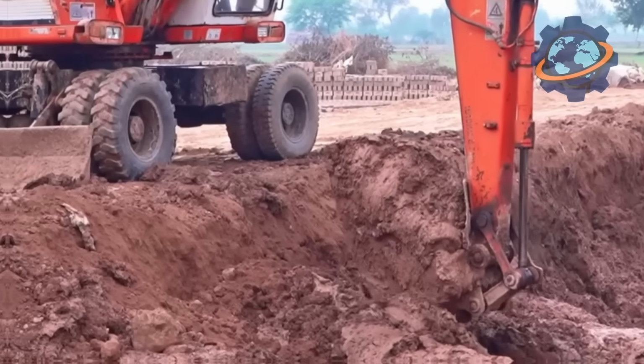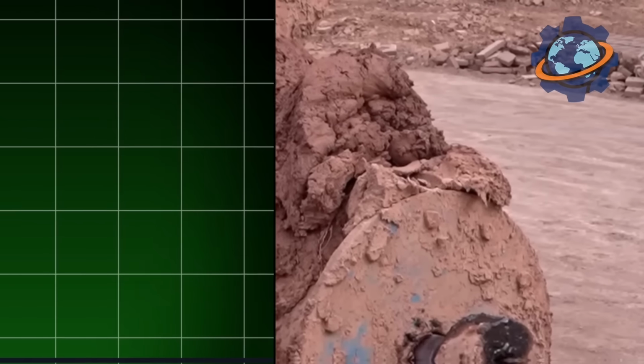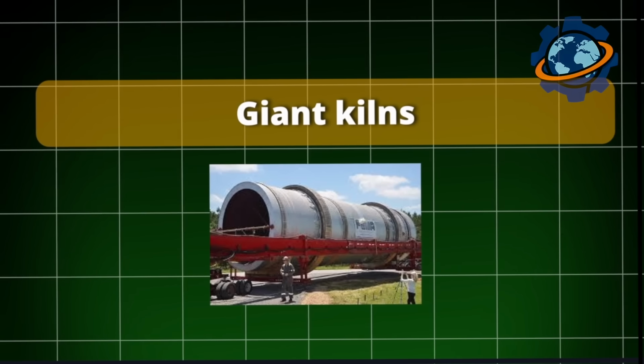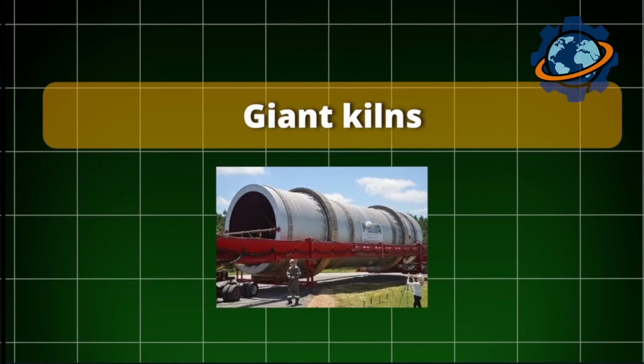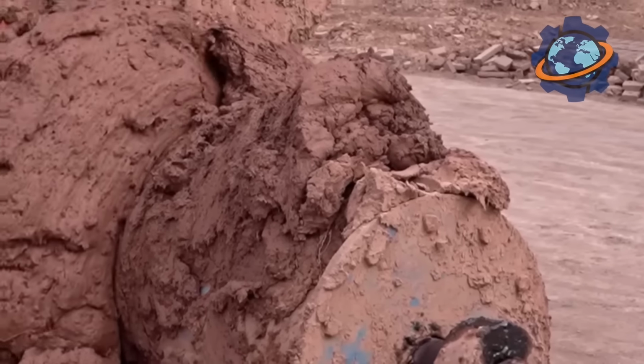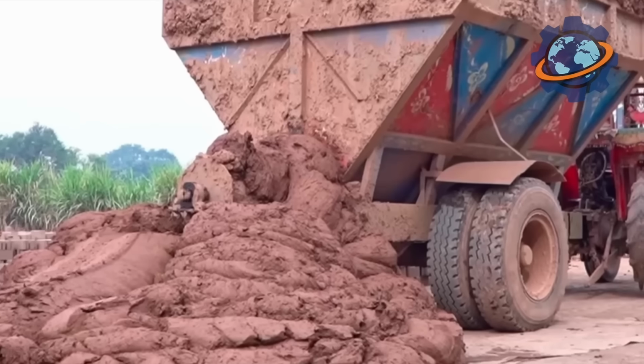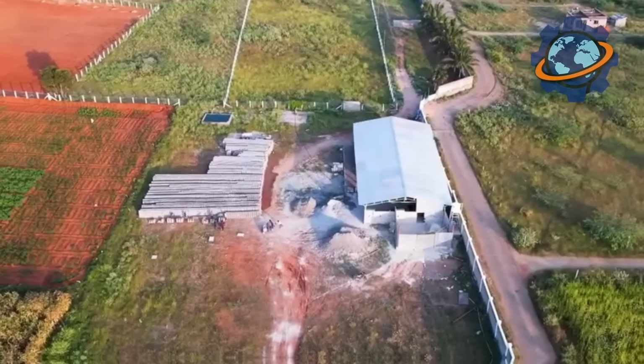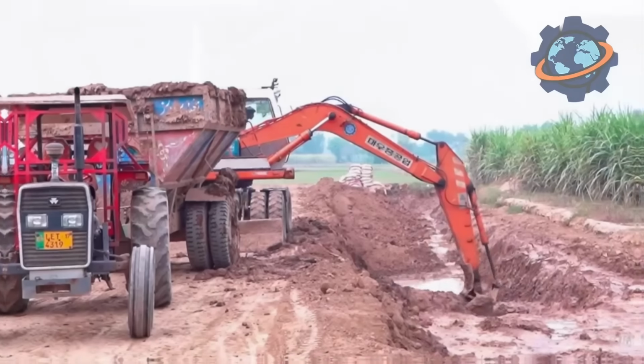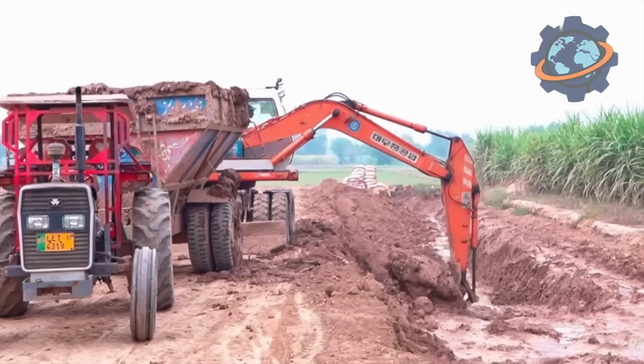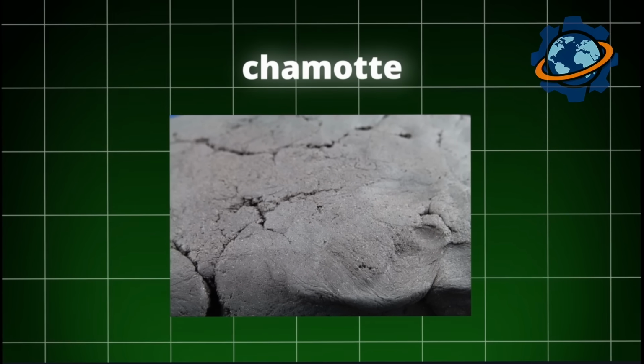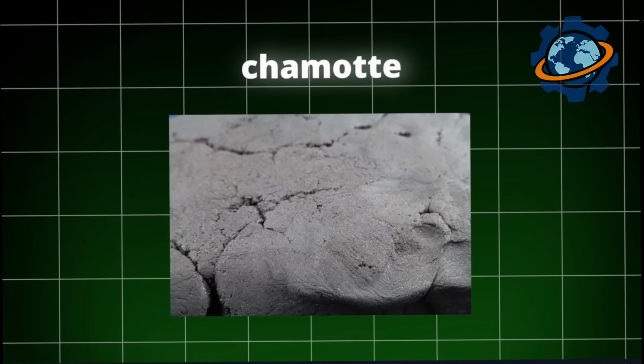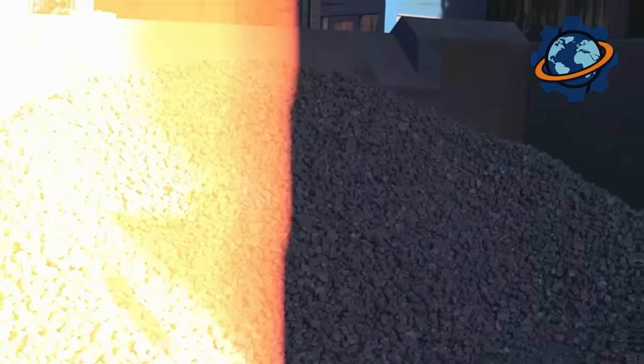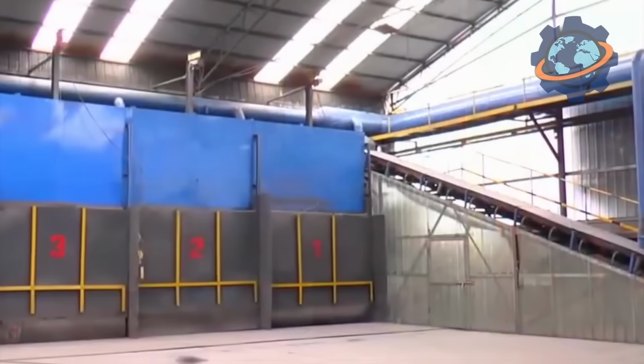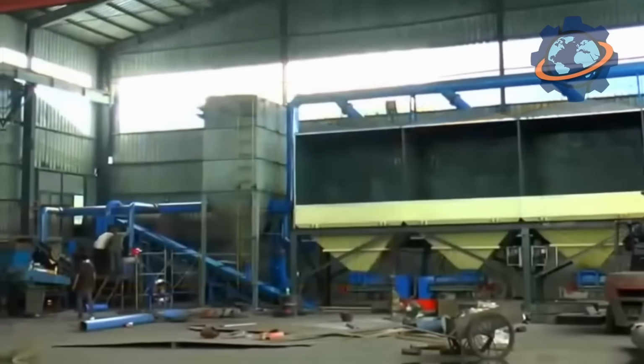Before making bricks, they destroy the clay. Giant kilns, tunnel ovens stretching 300 feet, fire raw clay at 2,400 degrees. The material transforms. Water molecules trapped in crystal structure evaporate. Crystals fuse together. The clay dies, becoming chamotte, fired aggregate resembling brown gravel. Watch workers dump glowing chamotte onto cooling floors. Steam erupts as residual moisture hits air.